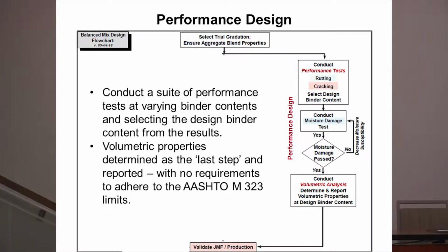And in the final one, which is a performance design, you're going to perform the suite of performance tests at various binder contents or various compositions, or let's say different levels of polymer modification or something along these lines. And then based on the results of those tests, you're going to select an optimum composition that you're then going to use for paving. In this case, the volumetric properties really are determined as the last step. And again, there's no requirement to adhere to the AASHTO volumetric properties at that point. So those are the three approaches that are out there, and various states have attempted each one of these, and I'll go into that in more detail later.